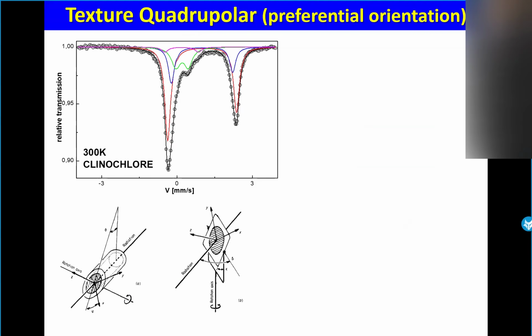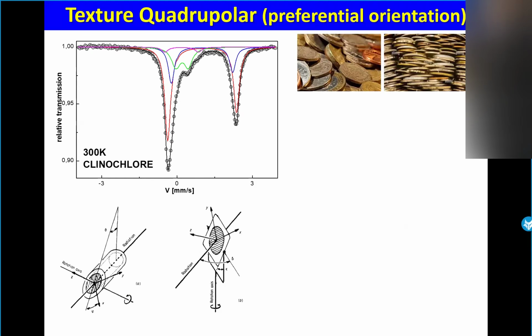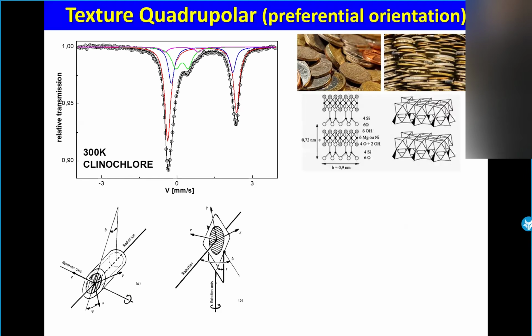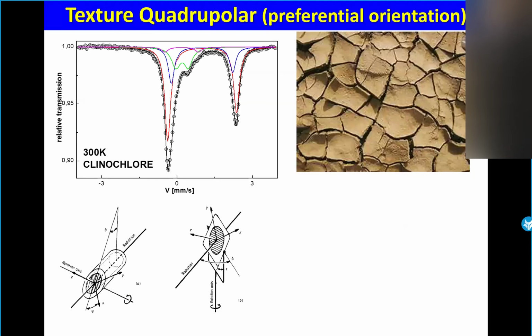So what to do? As you can see, you have money. If you put money over a substrate, it's difficult to have all coins oriented in the same direction. That means you will get a distribution, which is the same case in some minerals, which exhibit some layered structure with trioctahedral structures, typically of clays. So in this case, what we have to do is to check the texture effect.